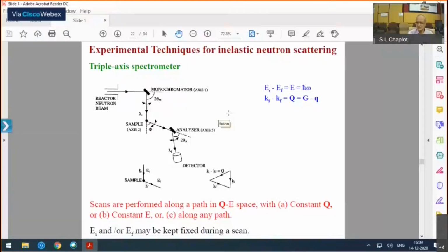It means out of the incident beam, 10% of the neutrons are scattered. So if I use more than that, then the chances are that you will have a first scattering, and then you may also end up having a second scattering. And then if you have a multiple scattering process, my signal may be corrupted. The corresponding spectrum that I get will be a combination of the two.